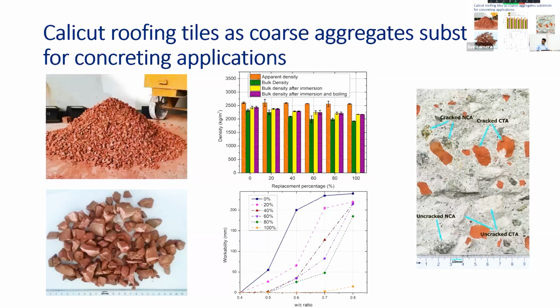The first one shows the density, how the density is going to vary with the percentage. Simply we can see that the density is going to be reduced, because calicut tile aggregates have low density compared to the normal aggregates. In addition to that, the workability is also reducing, but what we can do is use different admixtures to increase the workability.